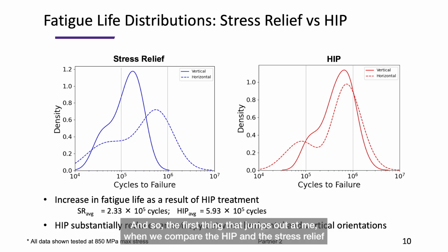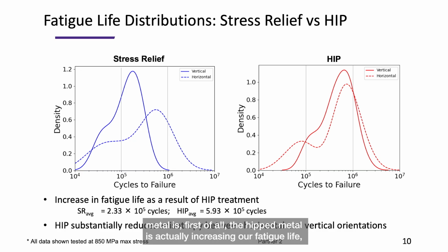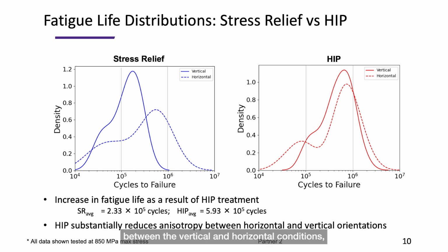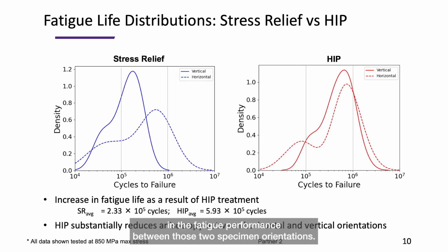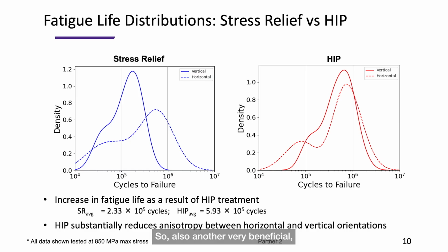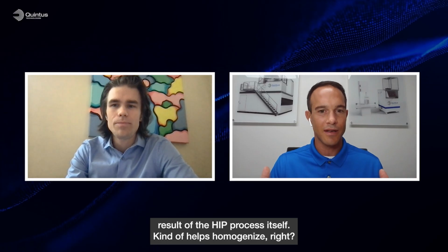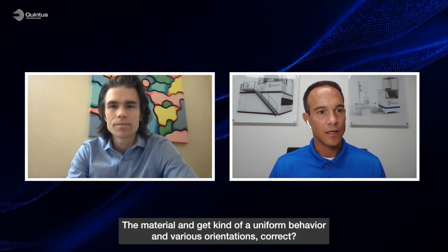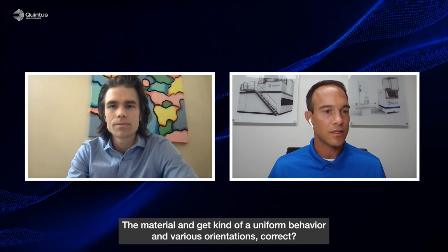And so the first thing that jumps out at me when we compare the HIP and the stress relief metal is, first of all, the HIP metal is actually increasing our fatigue life, increasing our number of cycles to failure, which is great to see overall. And then the next thing, interestingly, is if you compare the differences between the vertical and horizontal conditions, the HIP process is actually reducing the differences in the fatigue performance between those two specimen orientations. So also another very beneficial result of the HIP process itself. Kind of helps homogenize, right, the material and get kind of a uniform behavior in various orientations, correct?